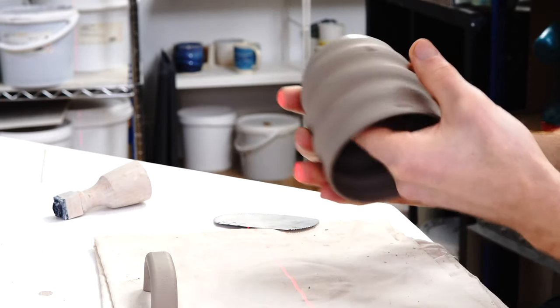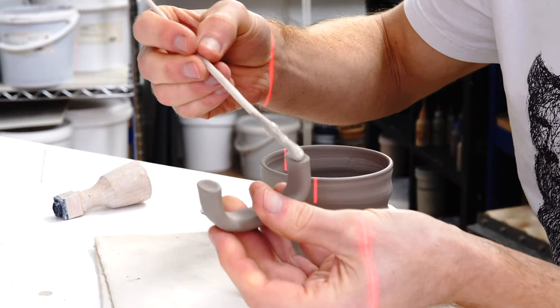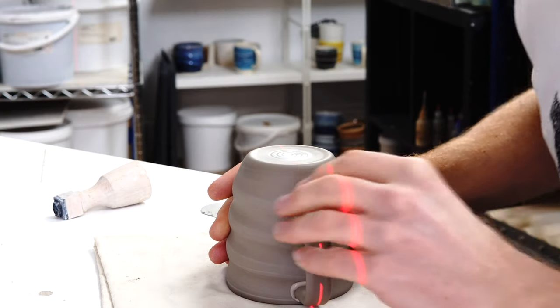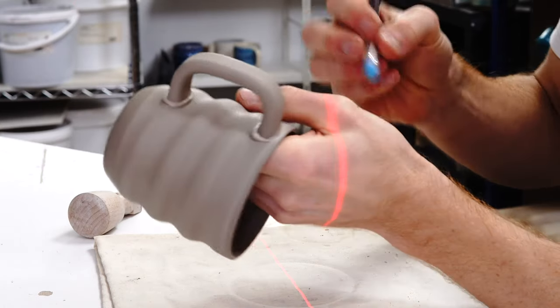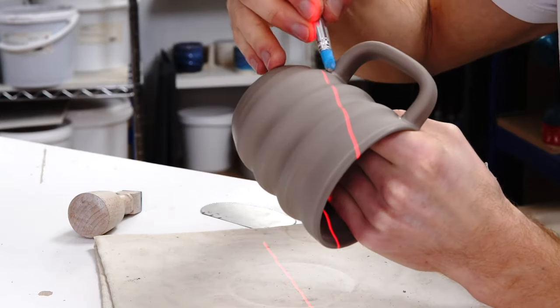The reason we don't want to have bubbles in the clay is that a bubble in the clay gets extruded out and either bursts at the surface level — so you can't use that section of extrusion for a handle — or it stays hidden within the handle until you go to bend it and then it ruptures at that point. So we want to avoid any air inside the clay.